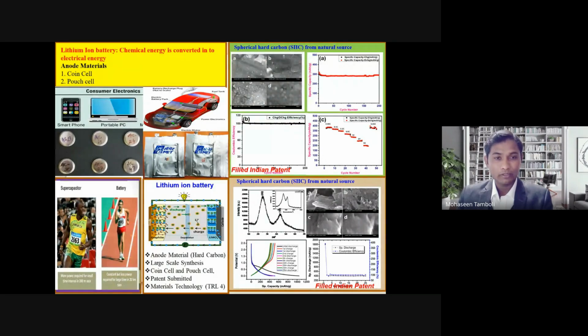We developed this in our laboratory previously at C-MET Pune during my doctoral course, and at that time we compared those results with commercially available graphite. Graphite is the commercially available material used in electronic components and commercially available batteries. We developed a hard carbon material which is quite competitive with that commercially available graphite. We have filed a patent. Our hard carbon shows high specific capacity and is more effective than graphite, with a specific capacity over 400 milliampere hour per gram.